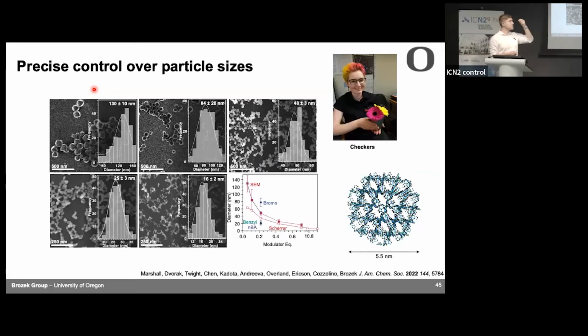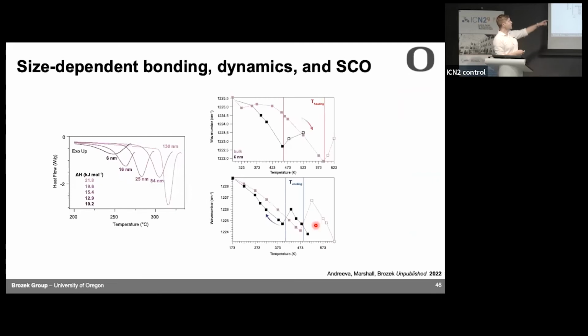By using methylimidazole as a modulator, we can use very few modulator equivalents, very, very little, and control the sizes from hundreds of nanometers down to just 5 or 6 nanometers, which is among the smallest, if not the smallest, reported MOF nanocrystal. These are also indefinitely colloidally stable, which is totally bizarre. I was talking earlier about how we don't add any surfactant ligands, and these are just indefinitely stable in DMF. We started this project about 1.5 years ago, and we have particles still sitting in DMF and nothing has precipitated out. So we can take these particles and measure their spin crossover temperature using differential scanning calorimetry.